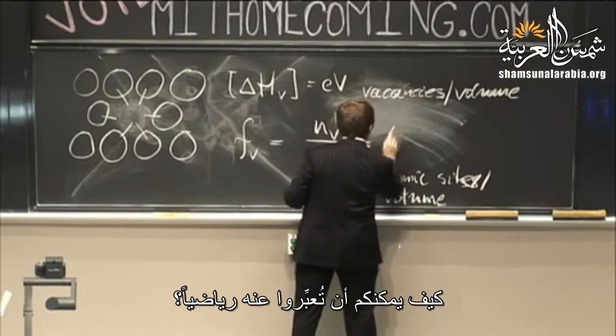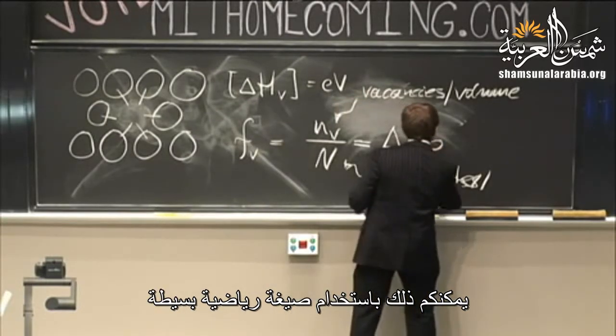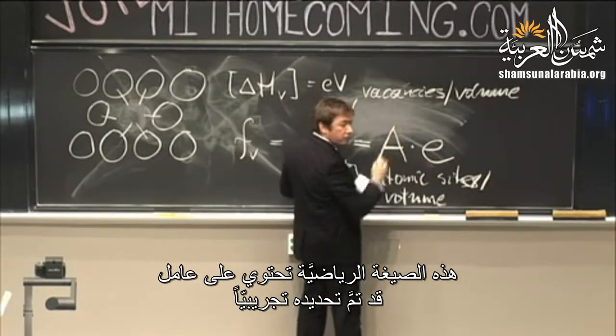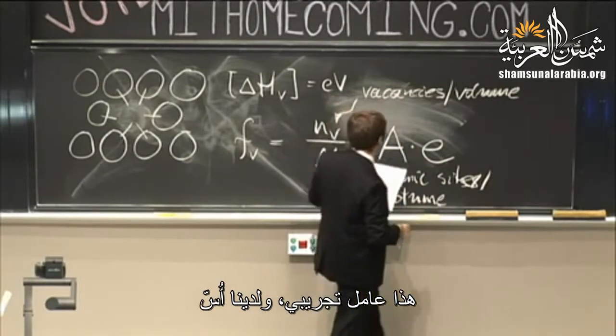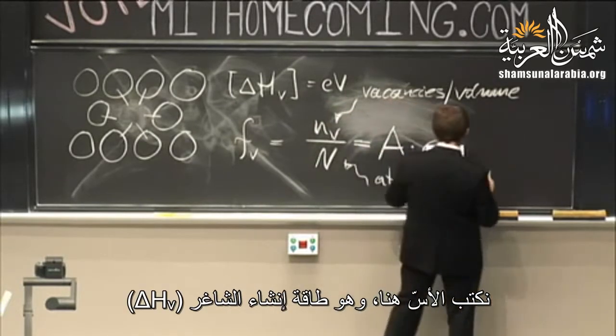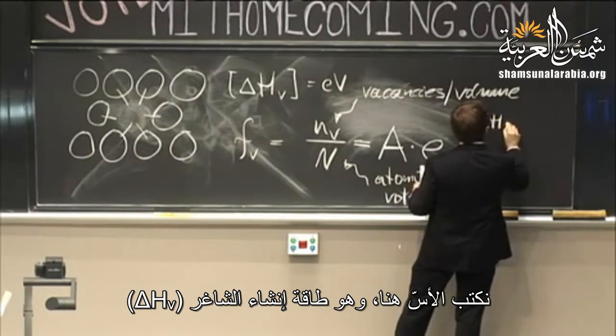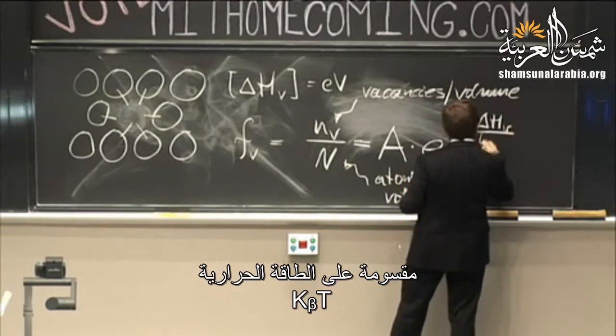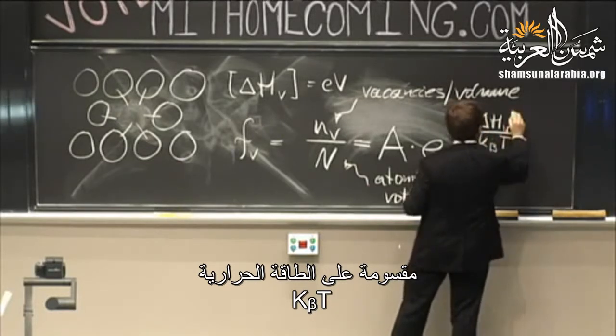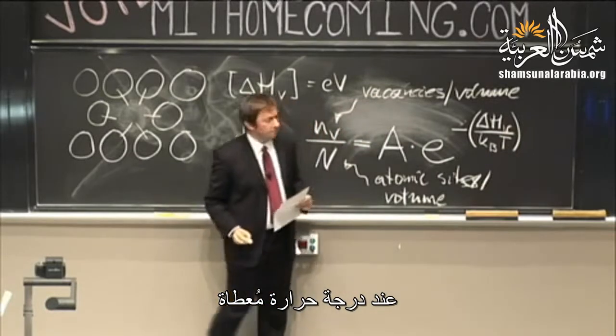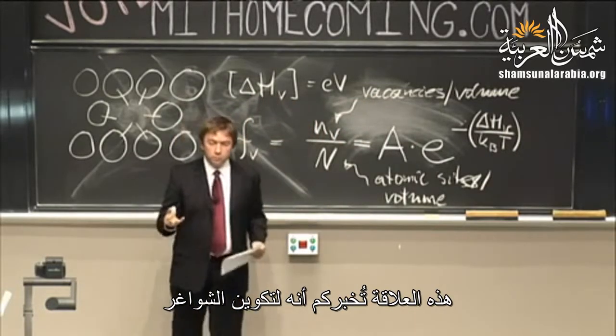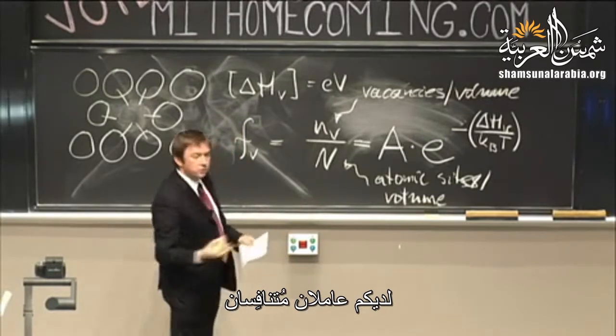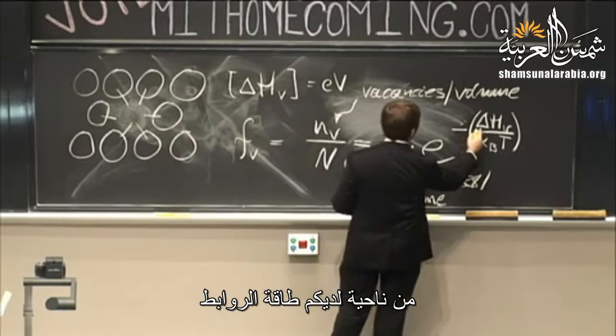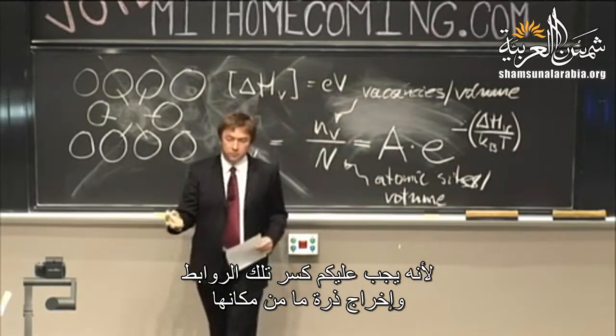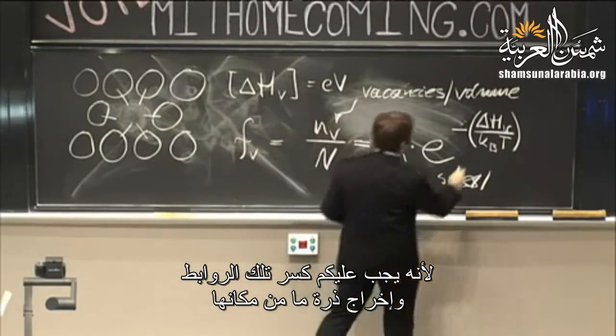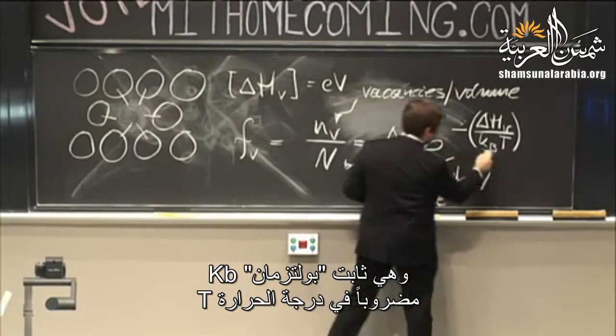And how do we express it? Well, we express it using a very simple formula. This formula contains a factor here, which is experimentally determined. This is an empirical factor. And then an exponential, so the exponent, we take here the vacancy formation energy, and we divide it by the thermal energy at the given temperature of interest, right? So this is actually telling you that to form vacancies, you actually have two factors competing with each other. On the one hand, you have the bonding energy that makes it difficult to form vacancies because you're breaking bonds, you're taking an atom out. On the other hand, you have this thermal energy, Boltzmann constant times the temperature, right?